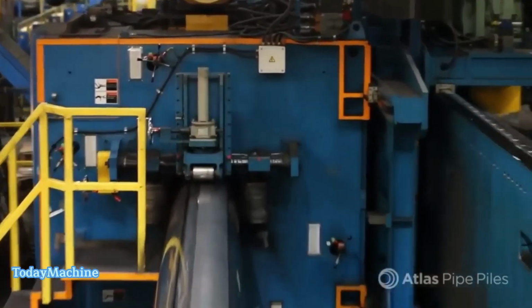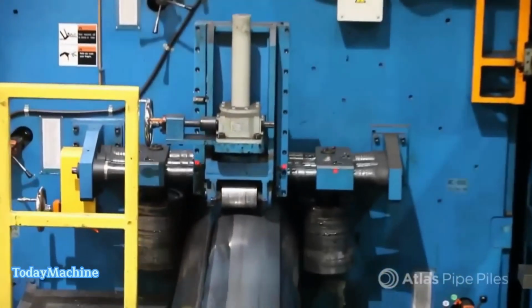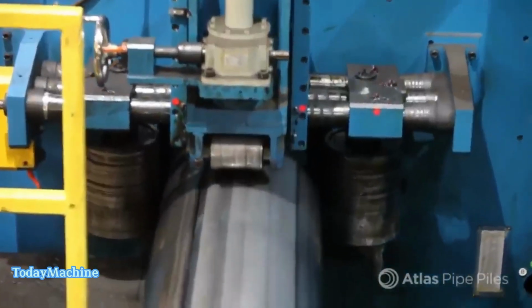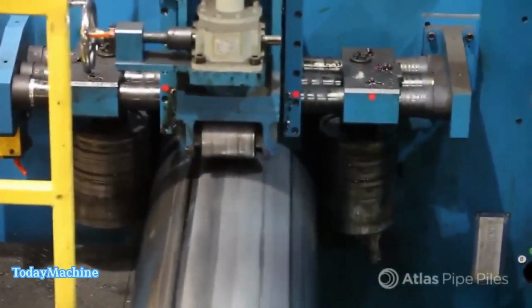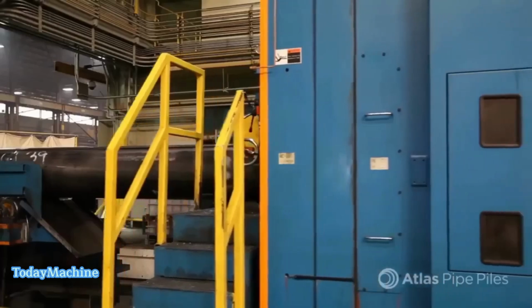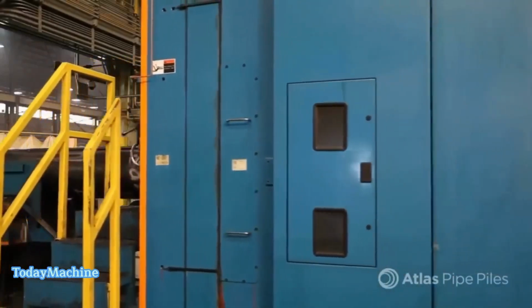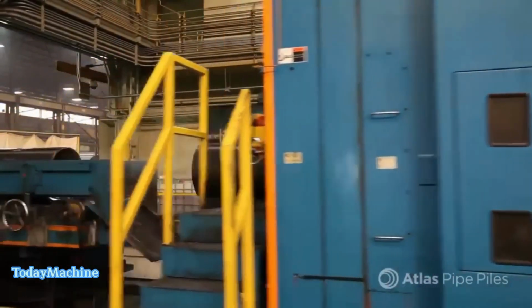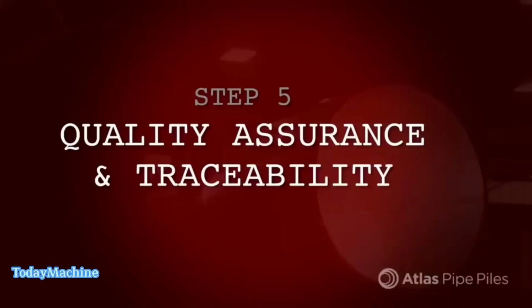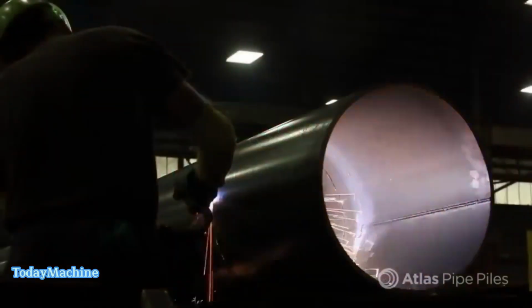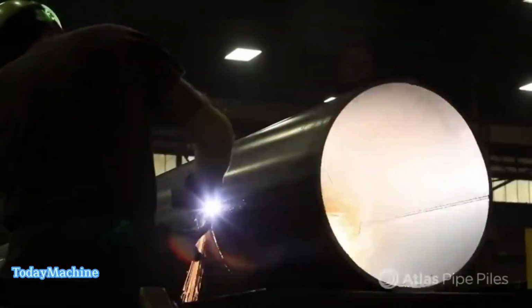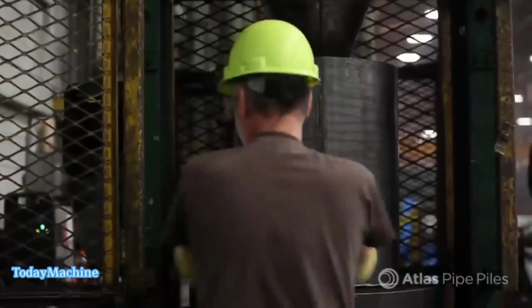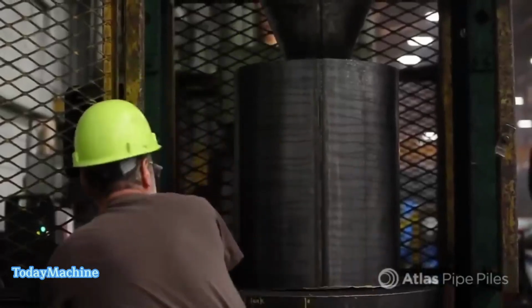The first is the burst test, where hydraulic pressure is applied to the pile until it fails or expands to a predetermined amount. This test verifies the weld's integrity and ensures that it can withstand the expected loads and pressures. The second test is the flatness test, where a sample of the pipe is flattened in both vertical and horizontal axes. This test verifies the weld's integrity and the ductility of the steel itself.